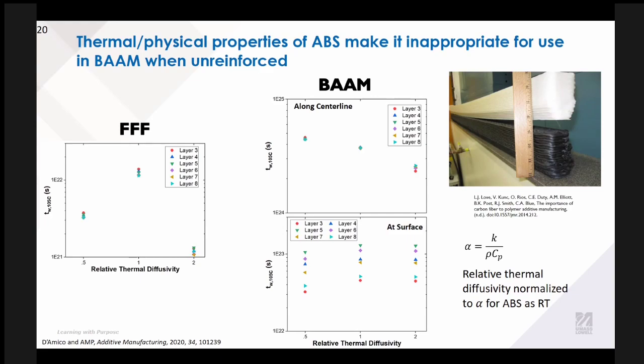And what we ended up seeing, if we look at our isothermal weld times, is that there isn't a huge difference between different relative thermal diffusivities that are normalized to ABS. So if we go from ABS to the chopped carbon fiber, in the center line there is a bit of a difference, but at the surface there really isn't. And that is very different from what we see in FFF, where there is this local maximum in the weld time at the relative thermal diffusivity that corresponds to that of ABS.